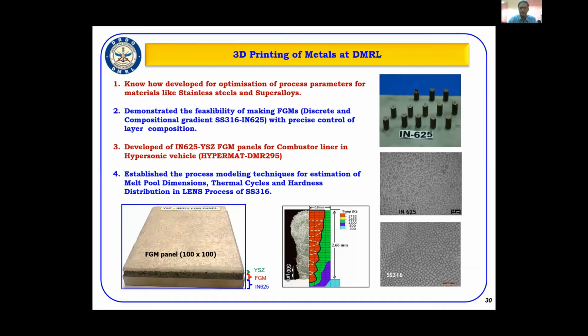So for almost all the materials we were handling, the optimized process parameters have been developed, and we have also demonstrated the feasibility of making FGMs using very precise control of layer composition in the materials SS316 and 625. We have also developed Ni-based/YSZ ceramic-based FGM panels for combustion liners for high temperature applications in hypersonic vehicles. And we have established process modeling techniques for estimation of melt pool dimensions, thermal cycles, and hardness distribution along the process for one of the materials. From this, I'll touch on one or two cases in the subsequent slides.